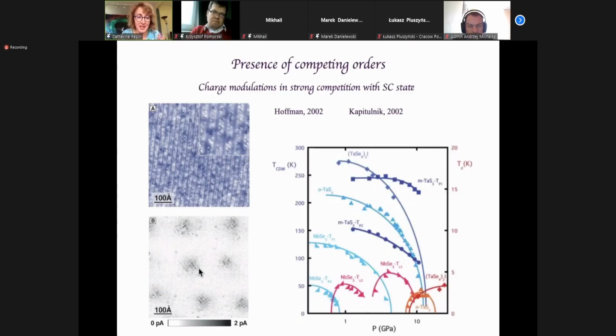This is typical. Inside the vortices, you should see what the normal phase is made of, basically what competes with superconductivity. For years, when people were doing theories of RVB or fractionalized phases, they were asking STM people, do you see antiferromagnetism inside? Do you see loop currents inside the vortices? Do you see d-density wave? Well, basically, they saw charge modulation. It's simpler than those complex theories, but it's charge modulations. So nature provides us with strong competition, with coexistence of superconductivity and charge orders.